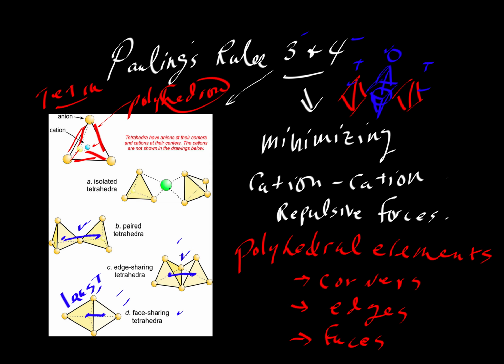Now there is a little bit of shielding. You can see that here. Those 2 oxygen atoms are allowing a little bit of electronic shielding between those cations, but it's not perfect shielding. So those cations can see one another. There'll be a Coulombic repulsive force, and they would push apart. You might imagine those being split away from that edge so that they would share corners instead of an edge. If we happened to force them into an edge sharing arrangement, it would be unstable and it might unfold itself into something like this.